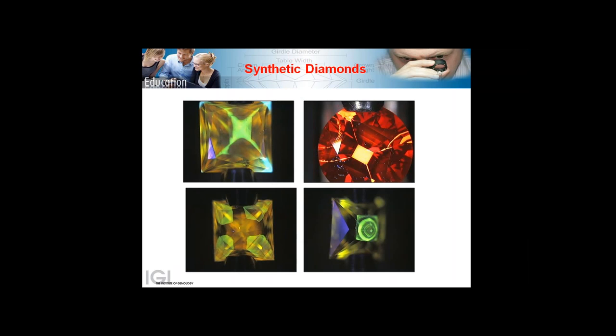Then you see synthetic diamonds. What was so different? You saw more layered growth before, and now you see a more typical cubic growth, which is very geometric, and that's a clear difference between a natural and a man-made diamond, seen under the DiamondView equipment. This cannot really be seen under a microscope. Also, what you see is a cross pattern. Do you see this? Clearly a cross pattern being seen. That is what also helps us determine that this is a lab-grown stone.